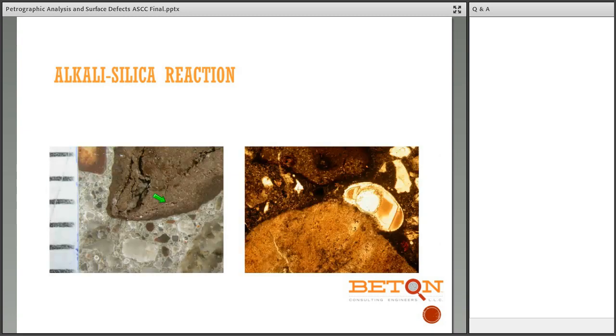But that type of crazing you saw on the pavement could also be freezing and thawing, or lots of other things, and this is one of the things a petrographer can tell you: exactly where the expansion is coming from. In this instance, you can see fractures coming out of the aggregate and going down into the paste, in which case you have a gel plug in this area. And in thin section, you get the fractures going through, and you also have a void here that is filled with alkali-silica gel.